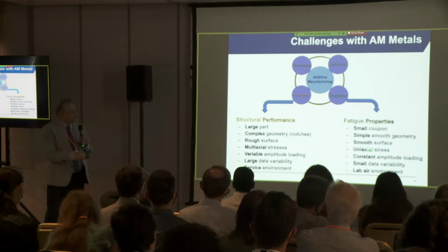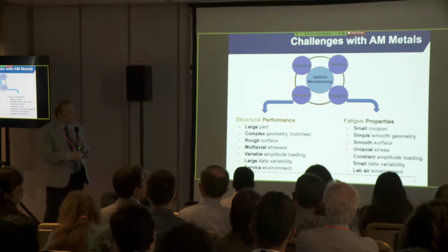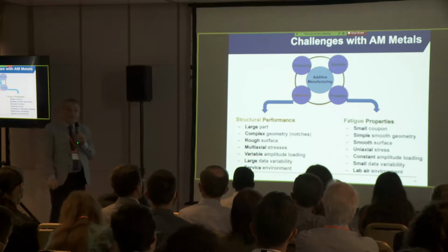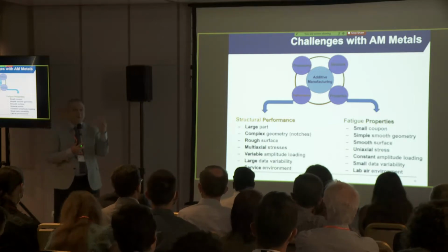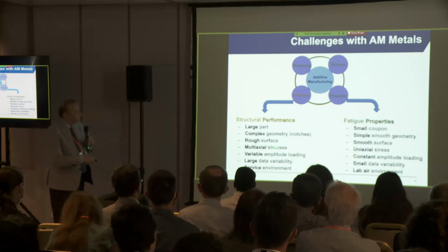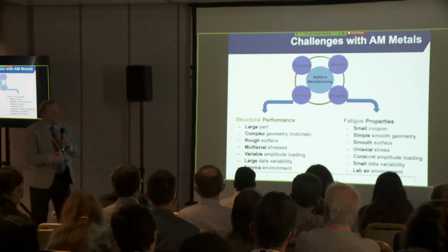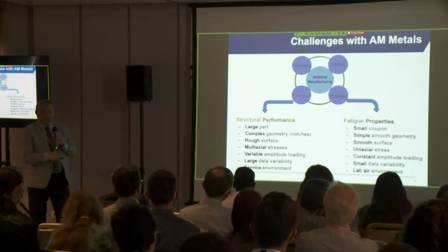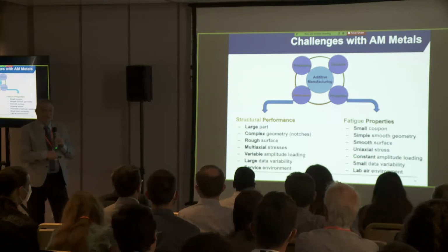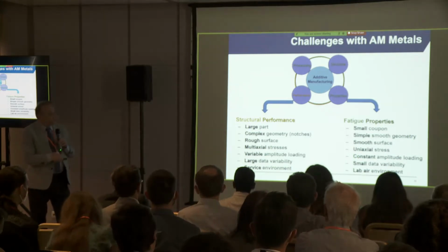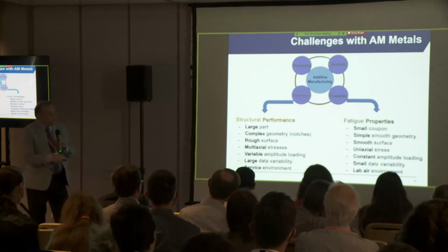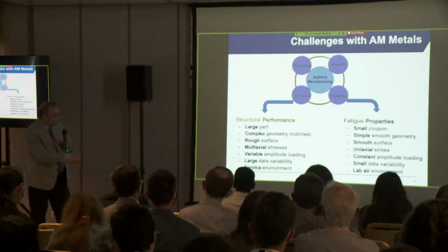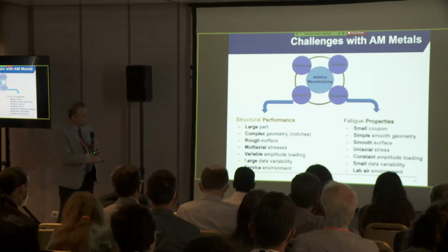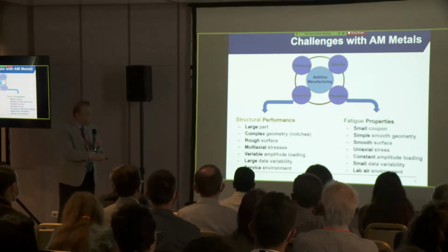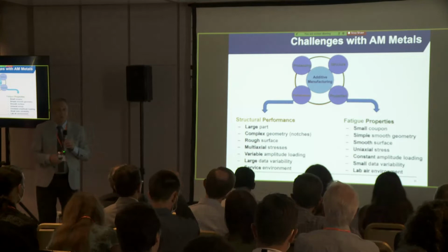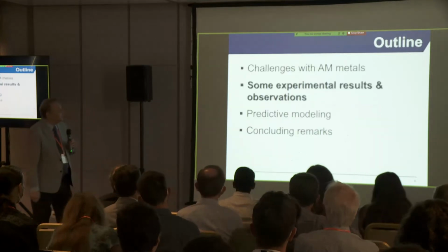The stress state for a simple coupon is uniaxial. In reality, we oftentimes have multi-axial stresses, because when you have a complex structure, multi-axial stress is nearly always there. In coupon tests, we deal with constant amplitude loading. In service loading, we typically have variable amplitude loading. In coupon tests, we deal with a small variability. In structural components, we have a lot more variability, and also environmental conditions. So these are some big differences.